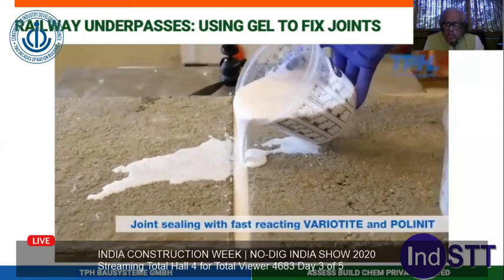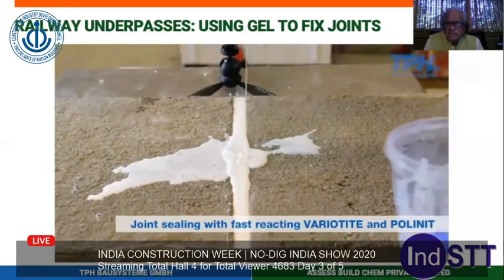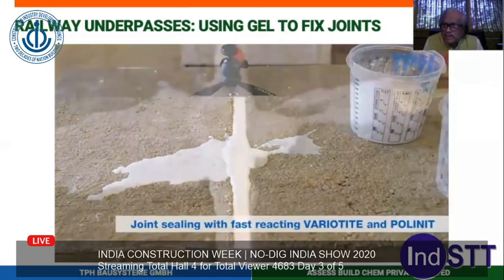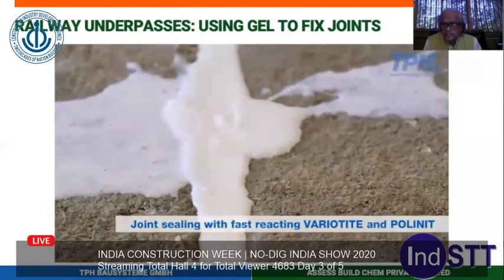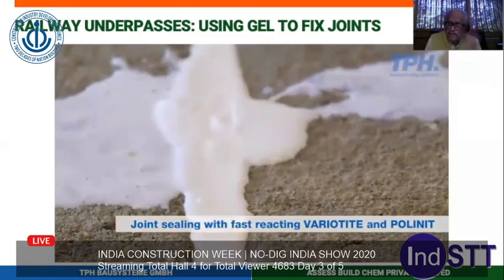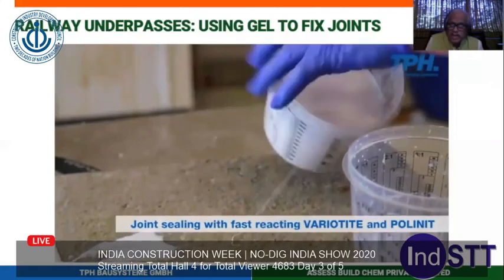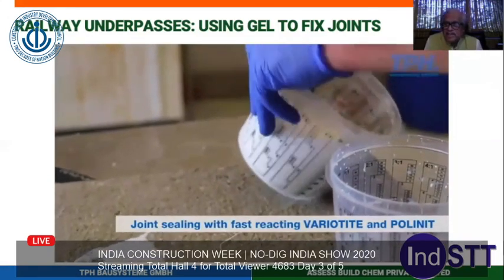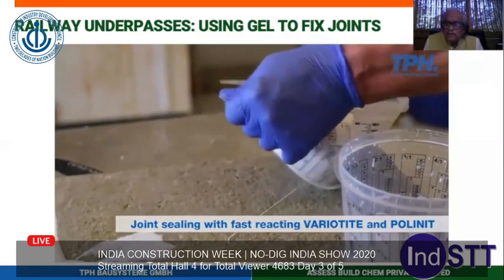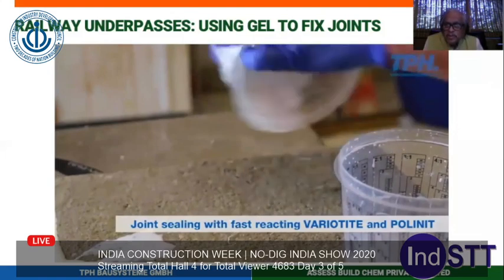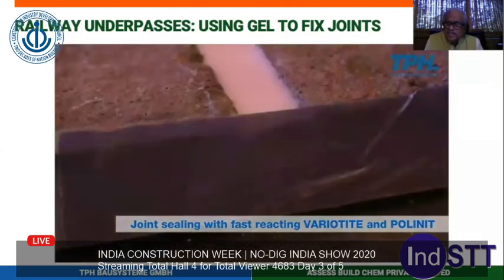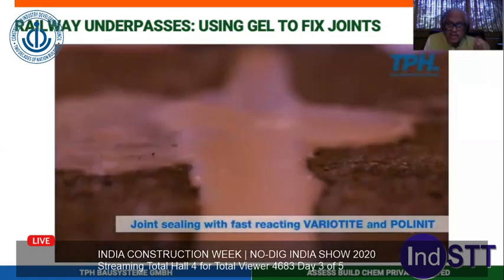It gels within no time. Finished. The material has already started gelling. It has already gelled. It is a 3-component gel: A component, B component, an accelerator, and fortified polymer. You can see here within seconds, within 10 to 15 seconds. And this is the material that is to go inside the joints.